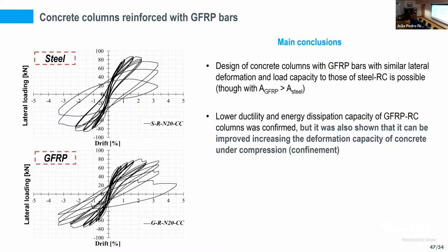These are the main conclusions that we obtained in this study. So we confirmed that we can design concrete columns with GFRP bars with similar lateral deformation and load capacity to equivalent steel reinforced concrete, although for that we need to adopt a much higher area of GFRP rebars as a result of the lower elastic modulus of the bars. We also confirmed the lower ductility and energy dissipation capacity of the GFRP RC columns, but we also showed that